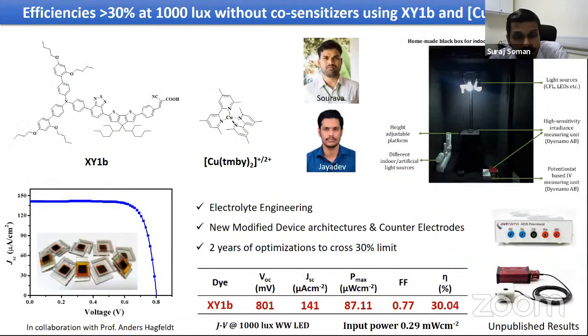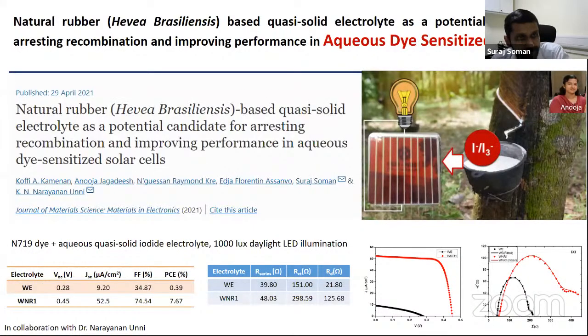And this is something that we achieved through the research in the last 2 to 3 years, in the copper electrolyte, where with custom tuned electrolyte engineering, the higher efficiencies currently reported are with multiple dyes, but by modifying the electrolyte, we were able to achieve around 30% efficiency. When I say 30%, you can see the power output is only 87 microwatt per centimeter squared, but this can be used for a multitude of applications. So this is one of the recent works that we had done.